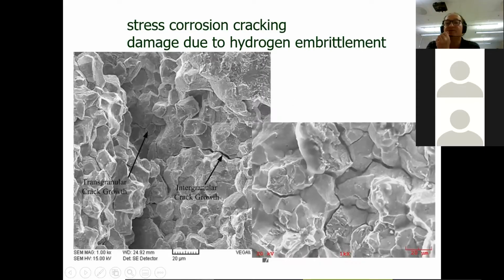And if you look under the microscope at the grains, this is a high magnification electron microscope image. In fact, there are 2 images together here. You can see the grains. I'm just drawing the cursor around a grain here. Here's another one. If you look carefully, there's a crack here, there's a crack here, and another one here, and another one here. And here you see some cracks as well. And here's some cracks. And there are two types of cracks marked on this micrograph.